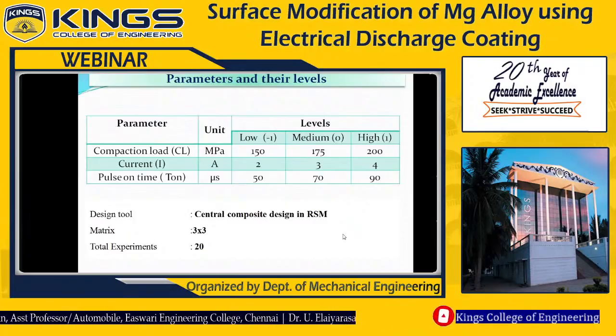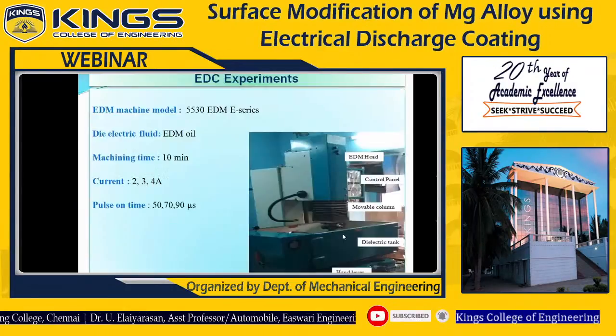I have given 3 levels for each: 150 megapascal, 175 megapascal, and 200 megapascal. The current range is 2 ampere, 3 ampere, and 4 ampere, and pulse on time 50 microseconds, 70 microseconds, and 90 microseconds. The design tool used for this research is central composite design of response surface methodology. The matrix is a 3x3 matrix. In total, 20 experiments are conducted to identify some of the properties. Okay, EDM experiment.